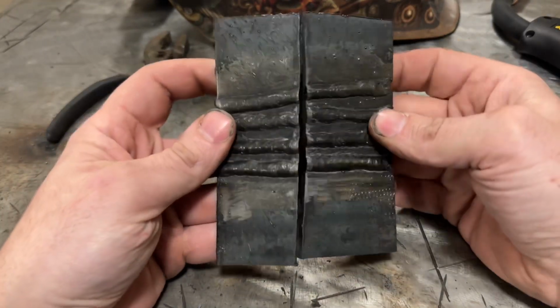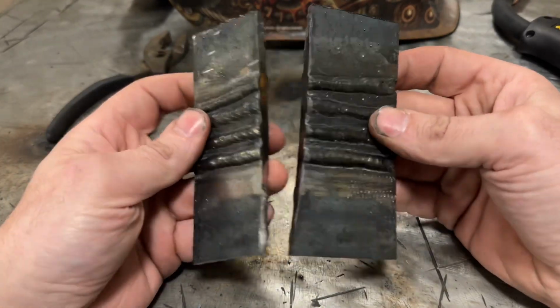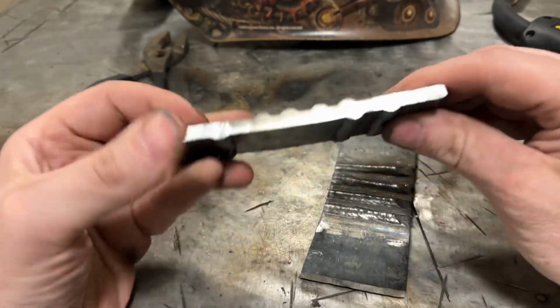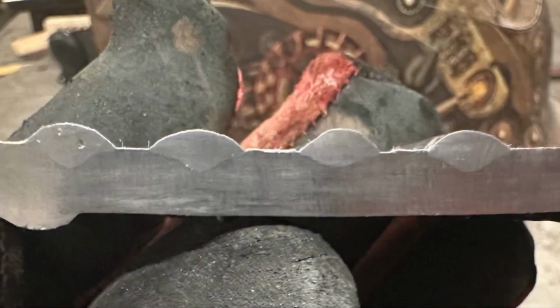Well, if the proof is in the pudding, here's the pudding. Let's take a look at this. So right away, what jumps out at me is the first pass, which was done without gas, has porosity that's clearly visible in it. I'm not too surprised at this. The settings that I was using with my welder are really a little bit on the cold side for 1/4 inch, and they don't recommend 030 wire for 1/4 inch.